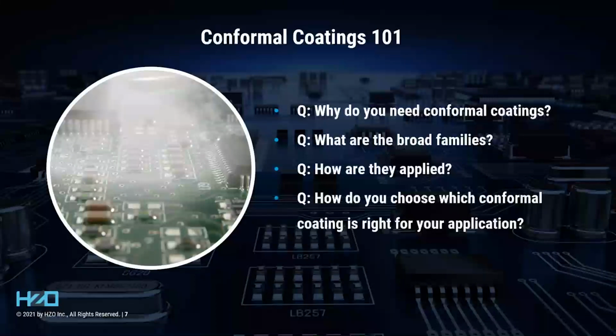How do you choose which conformal coating is right for your application? In my experience, conformal coatings tend to be an afterthought. They're added when you have mechanical or electrical or environmental failure that starts to occur. It's to fix issues with the overall design or the overall use case that weren't anticipated at the start. You need a conformal coating that solves your problem. It needs to wet adequately and be compatible with your substrate materials, and it needs to meet your standards, whether those are military, medical, FDA, automotive, UL.